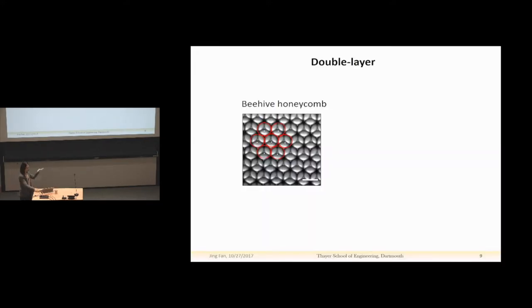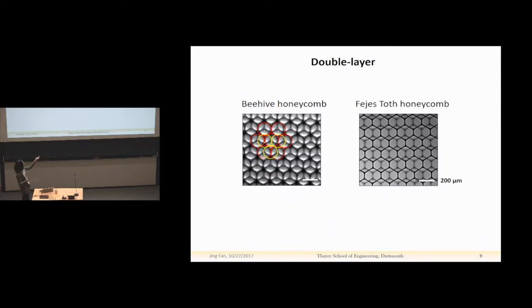And if the distance between the two plates is large enough, we have two layers of drops packed in between. And interestingly, when we have a relatively low volume fraction of the drops, we have this beehive honeycomb structure. So each layer of droplets is in hexagonal packing, and each drop locates in the center of three drops from the other layer, like this. And interestingly, when we increase the volume fraction of the droplets in this system, we saw the slip of one layer of drops by a half lattice. So each drop is still in hexagonal packing, but each drop is located in the center of four drops from the other layer. So the whole system structure looks like this. It's called the FT honeycomb structure.